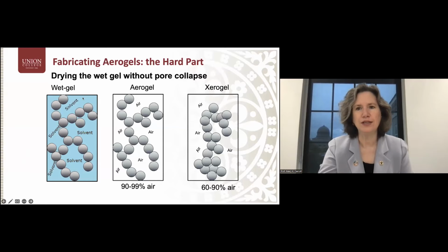So if we were using tetramethyl orthosilicate, the solvent mixture would be methanol and water. If we were using tetraethyl orthosilicate, the solvent mixture would be primarily ethanol and water. And so we have this solid matrix. If we can remove the solvent without the matrix collapsing, then we have an aerogel. And the aerogel by volume will be 90 to 99% air.